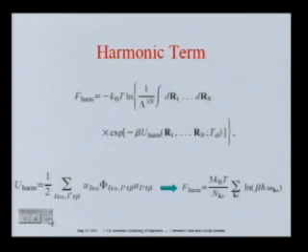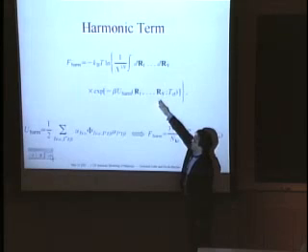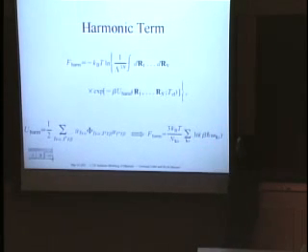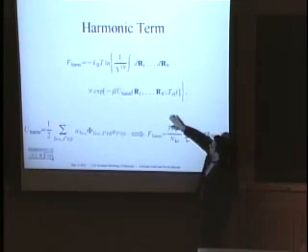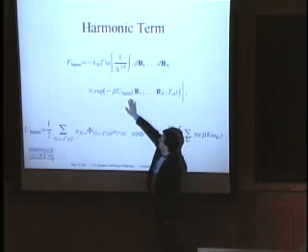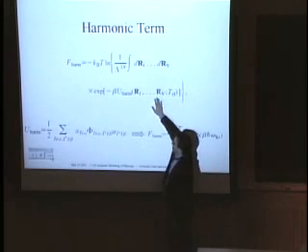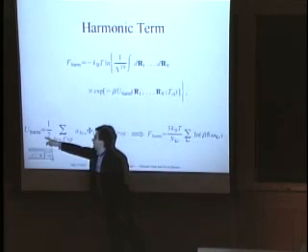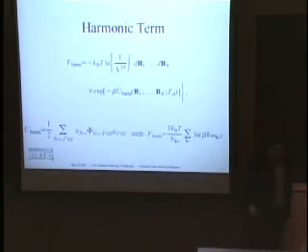So we could calculate, say for a solid system, the additional vibrational free energy that comes on top of the equilibrium ground state energy, coming just from the harmonic term. I haven't worked out the algebra explicitly, but it's fairly easy to do these integrals by writing the harmonic term in terms of the interatomic force constants.